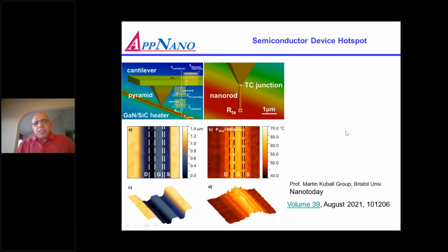Then another example is from the Bristol University group of Professor Kuball, and we made a very specialized probe for him because he wanted to go into these HEMT devices, which are made of gallium nitride on silicon carbide. We made a long nanorod which can go in, because the topography of these structures is very deep, like you can see from here. It's quite deep, and the thermal probe without these rods cannot go inside, and the devices are here. So they wanted to measure the temperature when they power these devices.